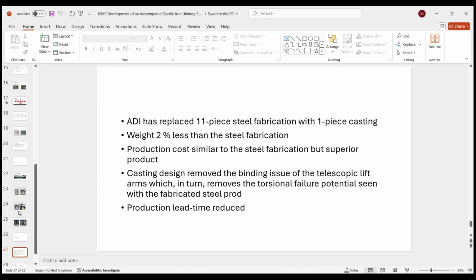So again, the conclusions of this: the ADI has successfully replaced an 11-piece welded fabrication. So I think it's very important, again, as foundries, whether it be iron, steel, aluminium, we can go out and say to the designers, you can change your fabrication to a casting, to a one-piece casting. Save yourself a lot of problems with regard to welding. Save yourselves a lot of problems of having to get 10 or 12 pieces of material together at one time, because if you have one part missing, you can't make the component. You take away the risk of the welds, and the additional testing of the welds, by putting in a one-piece component.